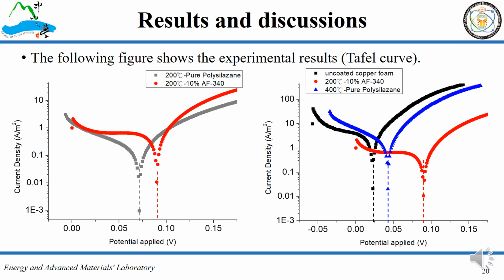This page shows the results of the Tafel curve. According to the left picture, we can see that AF340 can improve the corrosion resistance because the red curve has higher potential applied than the gray one. The picture on the right shows the PDC coating layer has corrosion resistance. The red curve has the highest potential applied in this experiment, with a pyrolytic temperature of 200 degrees Celsius and an AF340 concentration of 10%. The blue curve has the lowest potential applied among all the parameters, which is pyrolyzed at 400 degrees Celsius and coated by pure polysilazane. But they all have higher potential applied than the black curve, which represents the uncoated copper foam.